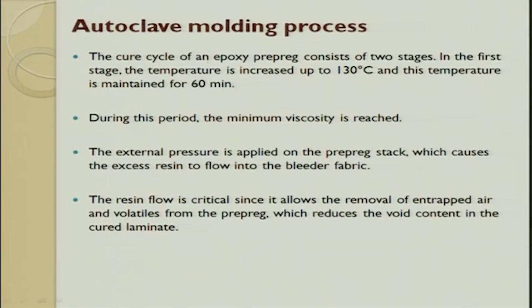The curing cycle for epoxy is always done in 2 stages. The first stage, the temperature is increased up to 130 degrees, and it is maintained for 60 minutes. As I told you, pressure, temperature and time are very, very important in any furnace. So here also for epoxy it is 130. If you add fillers to it, this changes, and the time also changes.